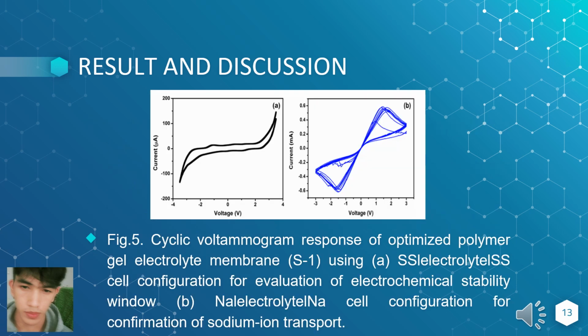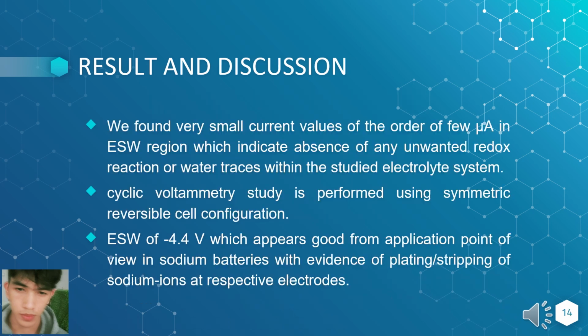So figure 5a shows the result from the analysis, which is SS|electrolyte|SS cell configuration for evaluation of the electrochemical stability window, and B, sodium electrolyte cell configuration for confirmation of sodium ion transport in the electrolyte. On close inspection of figure 5a, we found a very small current value of the order of a few microamperes in the electrochemical stability window region, which indicates absence of any unwanted redox reaction or water trace within the studied electrolyte system.